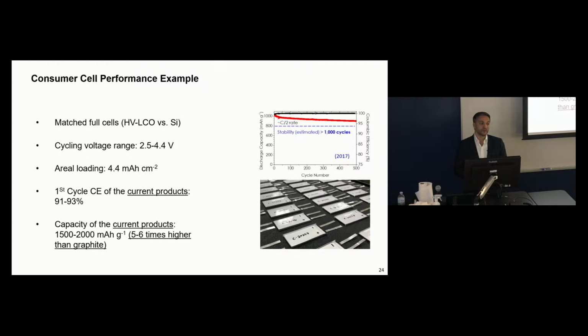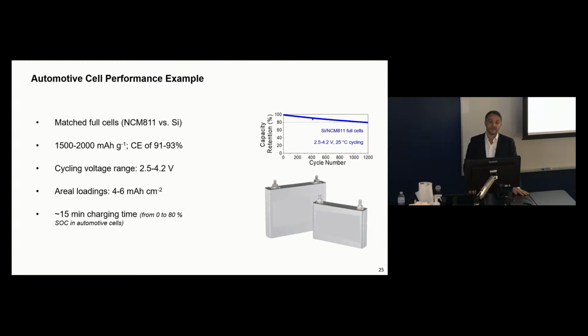So our materials offer about 5 to 6 times higher gravimetric capacity compared to graphite. Because it's a composite, not pure silicon, it's not as high, but in terms of volumetric capacity improvement, it's almost comparable to pure silicon. And this is an example of an automotive cell, again, over 1,000 cycles. So if you have a vehicle with, let's say, a 300-mile range, 1,000 cycles means it can drive for 300,000 miles. Again, typically sufficient for many applications.